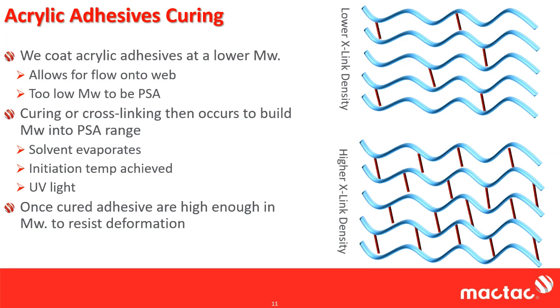Another way of doing this is initiation temperature. Sometimes they're out there. They're not very prevalent, but they still do exist. Now you have reactive groups on the back of your polymer. You get the web up to a certain temperature, that kicks off a reaction. That reaction cross-links the adhesive. Or the other way is UV light, where you put it down as a molten syrup type viscosity, and you hit it with UV light. And what all 3 of those are doing essentially is you're building the molecular weight to the point where you're back into the pressure sensitive range.